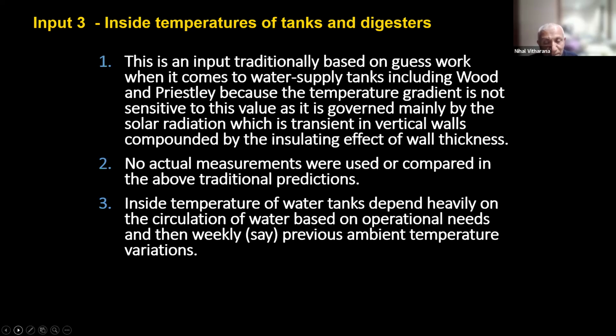The best parameter is the ambient, because water is coming from a dam or somewhere or a pipeline. Previously, like in New Zealand, they assumed that the inside temperature is always equal to the 6 a.m. temperature of that day. It doesn't show to be correct when we look at the data we got from the client's portfolio, but again, it doesn't make much difference. So what I have tried is calibrating with the average temperature of the previous 6 days as the initial temperature for the tank.